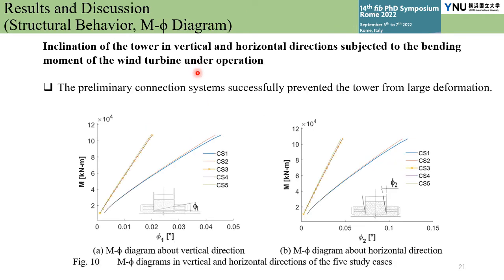The inclination of the tower in vertical and horizontal directions subjected to the bending moment of the wind turbine under operation is presented in the M-φ diagram. In case 1, the tower deformation has increased linearly in proportion to the applied bending moment. Similarly, case 2 shows smaller deformation because a higher reinforcement was implemented. For case 3, 4, 5, the linear graph has changed to a steep slope due to applying the designed connection system and prestressing force. It shows much smaller tower deformations in both directions compared with case 1 and case 2. This could imply that the connection system and prestress design successfully prevent the tower from large deformations.